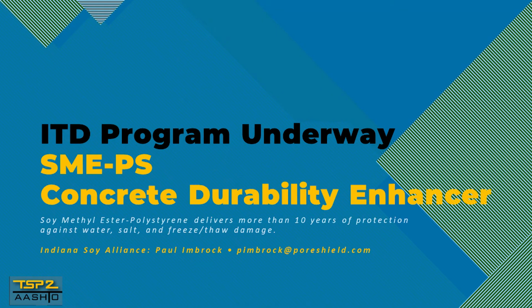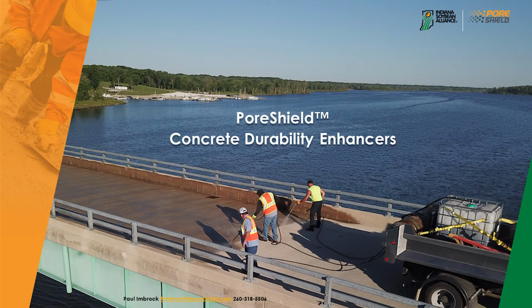Brings me to the SMEPS. This is a product that we got on the ITD program about 2 years ago. It's a soy methyl ester polystyrene, soybean oil-based treatment that fills a concrete pore structure and protects at least 10 years. This product can be used as an admixture with concrete or as a standalone product that can be spray applied or painted on. This particular bridge shows 23,000 square feet, and it was treated in 50 minutes.